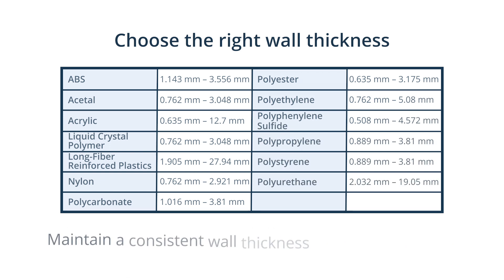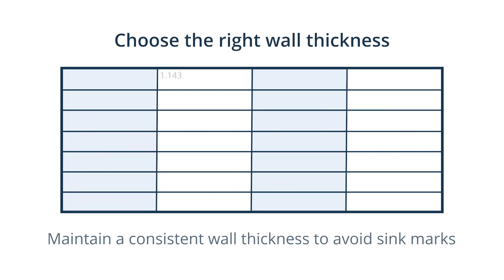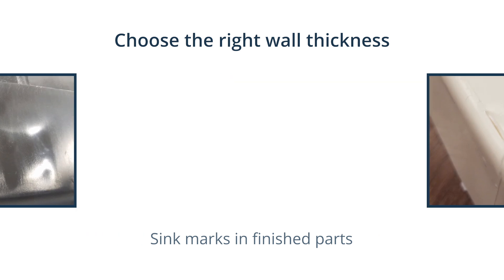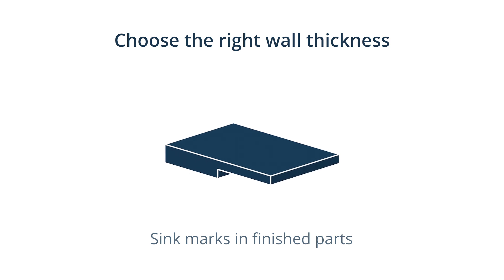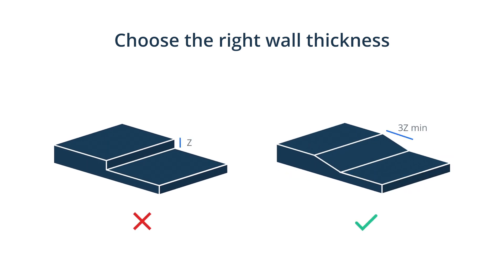Unlike CNC machined parts, plastic injection molded parts benefit from a consistent wall thickness. If a part is thicker in one section than another, a sink mark will appear at that location. Non-uniform wall thicknesses also lead to warping, as these walls cool and shrink at different rates. If you require a non-uniform thickness, the change in thickness should not exceed 15% of the nominal wall thickness and should always have a smooth or tapered transition to achieve a high-quality part.